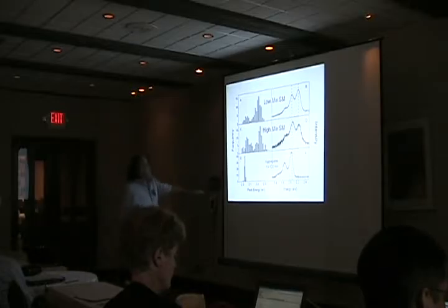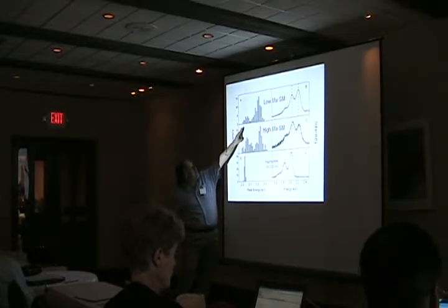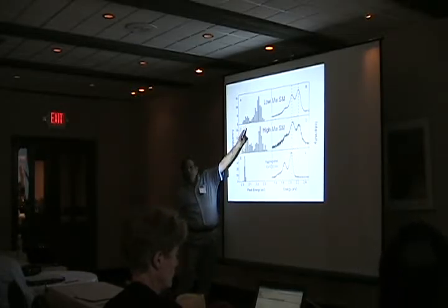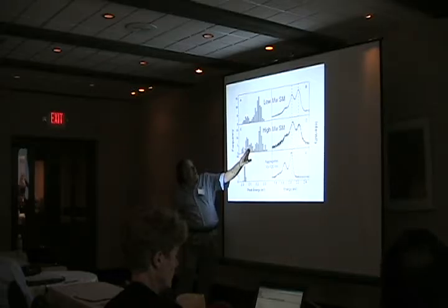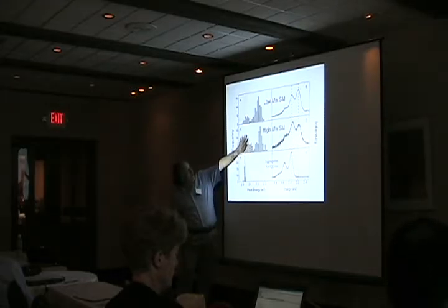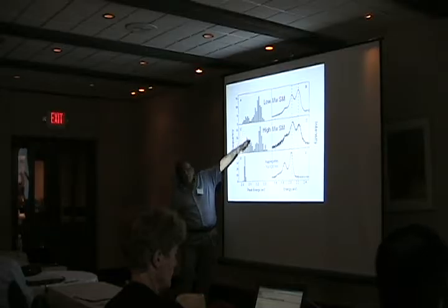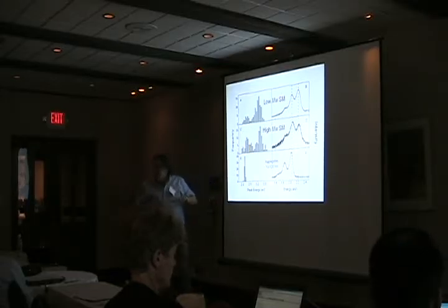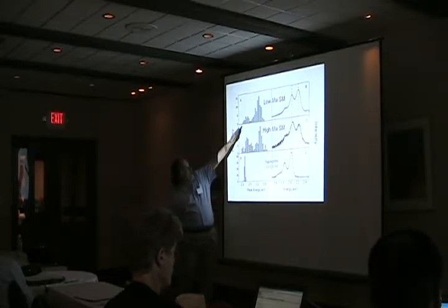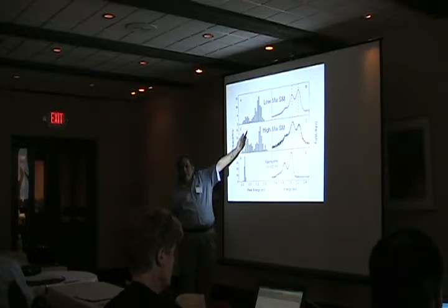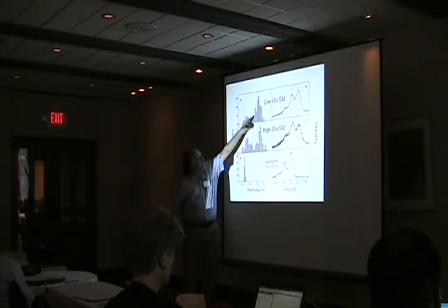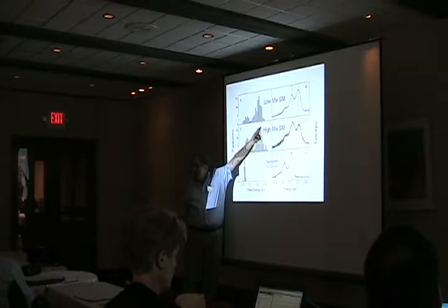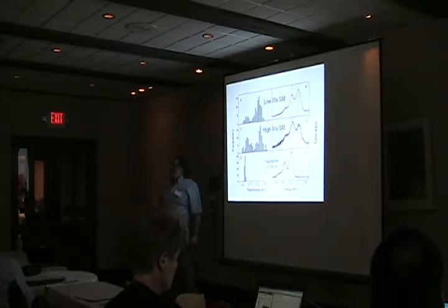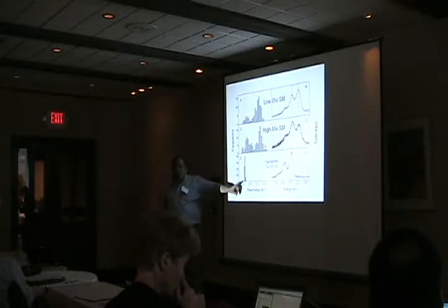Now, what I did want to show you is that for low molecular weight polymer, you get the red and blue site. For high molecular weight, it doesn't quite show up here, but you tend to get more of the red site. This is a little bit lower because you're allowing this morphology to form. For oligomers, which don't have the ability to fold on themselves, you only get the high energy side. And then you take about 50 polymer chains and assemble them together by a chemical technique, co-precipitation, and look what happens to the energy spread.